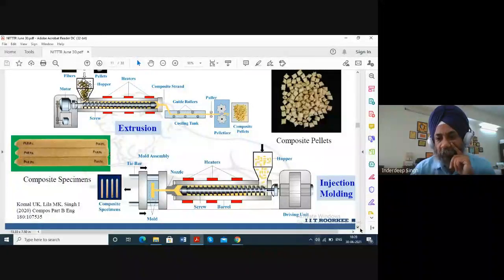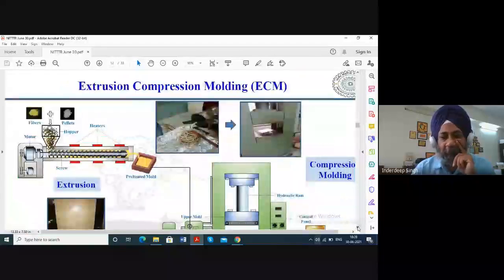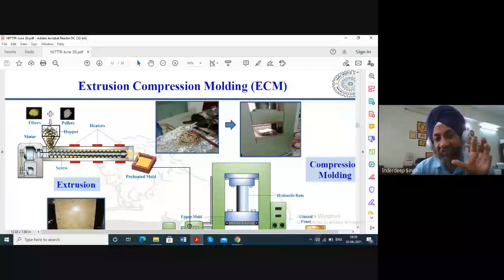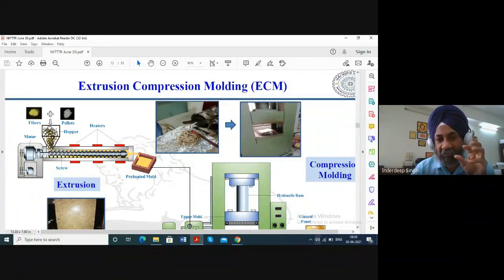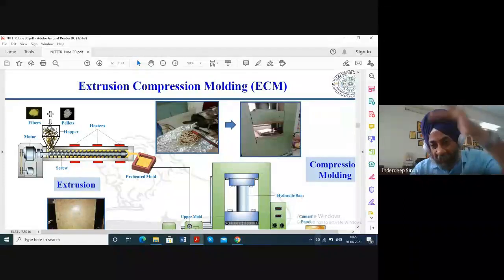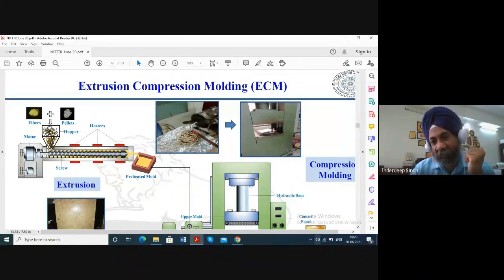If you go to the next process, you will see that the material is getting collected in a preheated mold. So here, instead of cutting it down or pelletizing it into smaller composite pellets, we are collecting the extrudate. This is the extrudate you can see coming out from the extrusion. This is collected in the preheated mold, and the mold is taken to the compression molding machine where pressure is applied on the material and composite plates are fabricated.